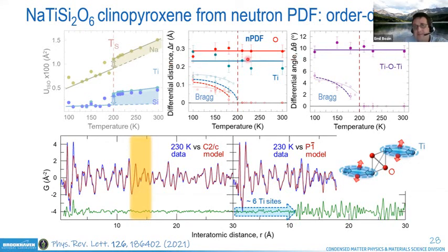So based on neutrons, you would basically conclude that there are actually distortions similar to or identical to those corresponding to the spin singlet order dimer regime, which it turns out is not the case. Part of the complication is also that the distortion that is associated with the dimerization is opposite for titaniums that get closer together and lateral oxygens that move away, and the signal from this gets overlapped.